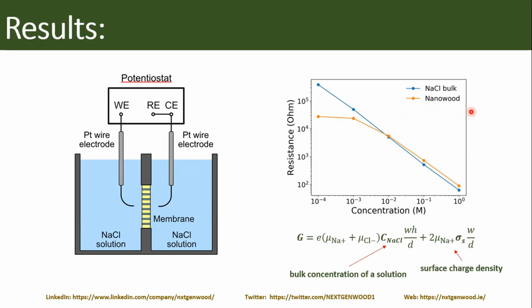So if we take this very general equation for conductivity of electrolyte inside of a nanochannel, we can see that it looks like this. So we have two terms here. One is representing bulk conductance. So we have here mobility of ions, concentration of electrolyte, and geometric parameters of our cell, like width, height, and distance between electrodes. And this term is representing conductivity due to a surface charge effect. Here we have surface charge density, width, and distance, or in this case, it's length of the electrolyte nanochannel. And of course, if we go to very high concentrations of electrolytes, this will dominate.